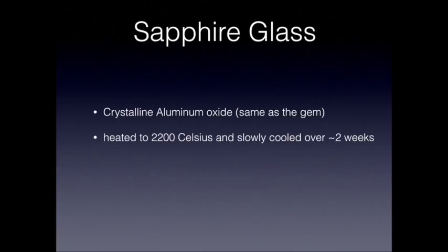Now let's move into sapphire glass. Sapphire glass is a little bit of a misnomer — it's not really glass and it's not made of sand. It's actually made of crystalline aluminum oxide, the same stuff that makes up jewelry sapphire. Sapphire has different colors due to various impurities in the aluminum oxide crystal, but for production of clear sapphire it's essentially pure aluminum oxide. You heat it to a very high temperature — about 2200 degrees Celsius.